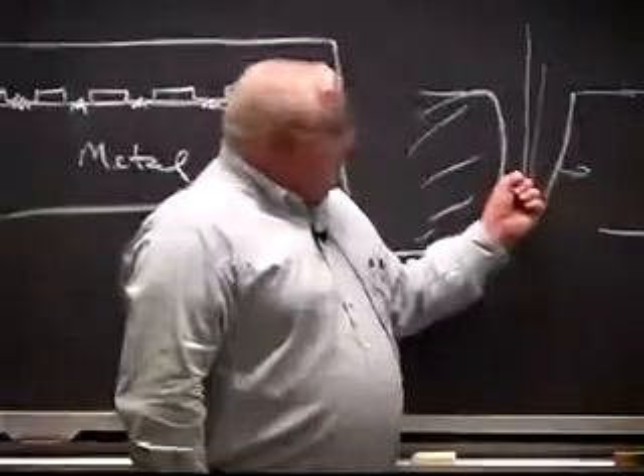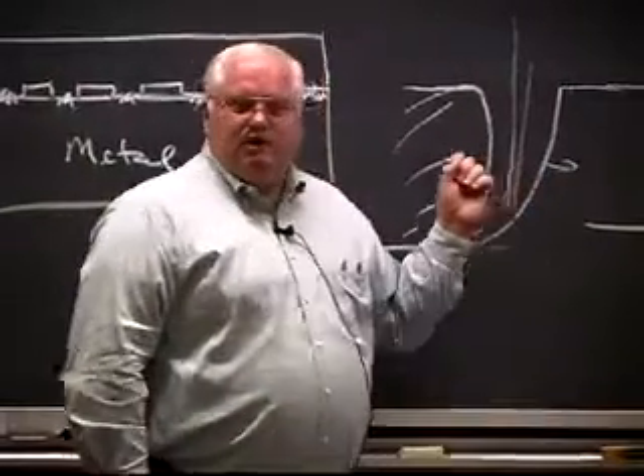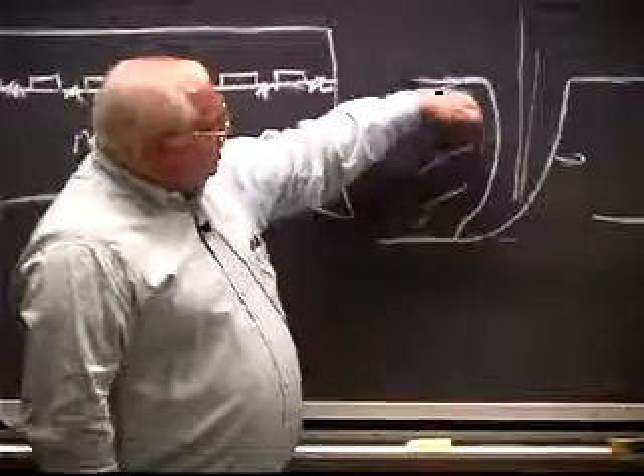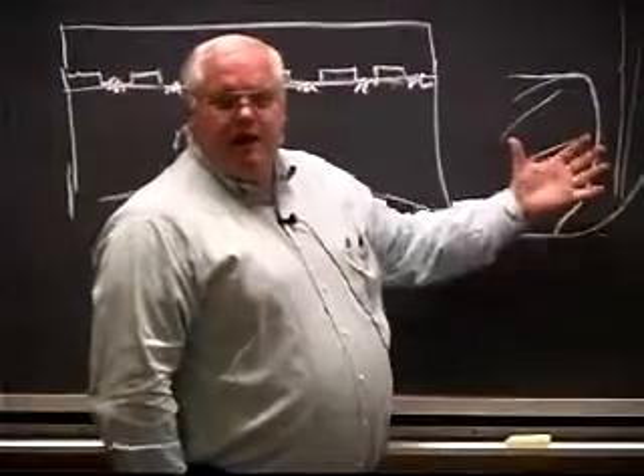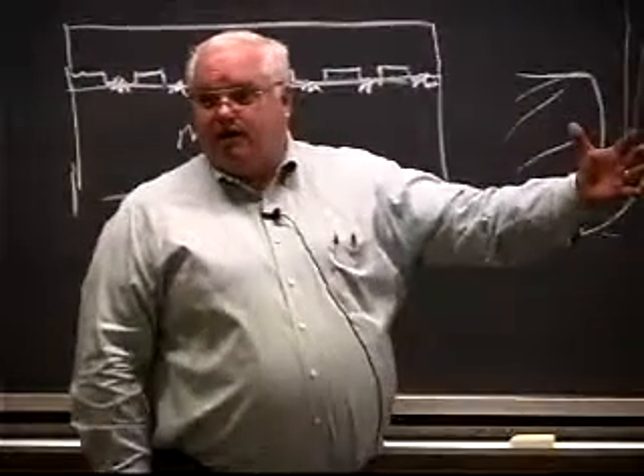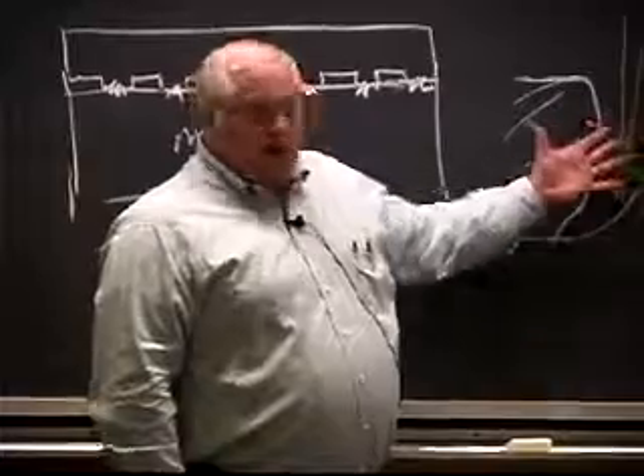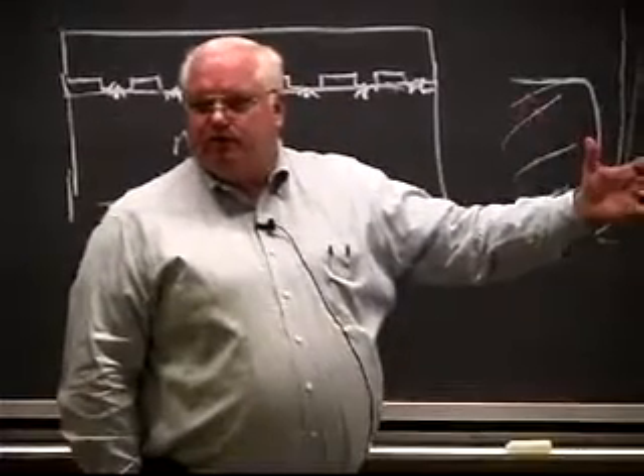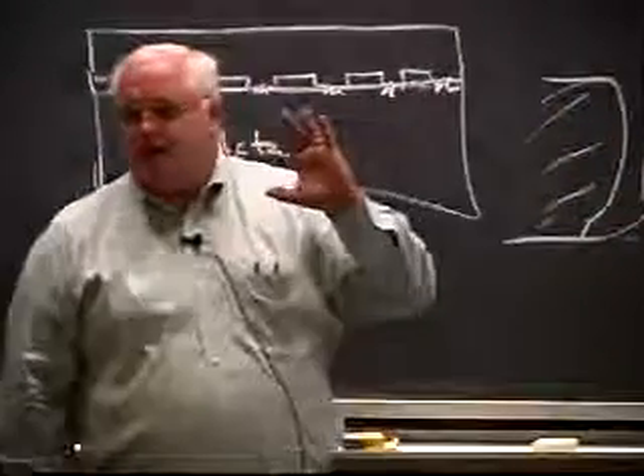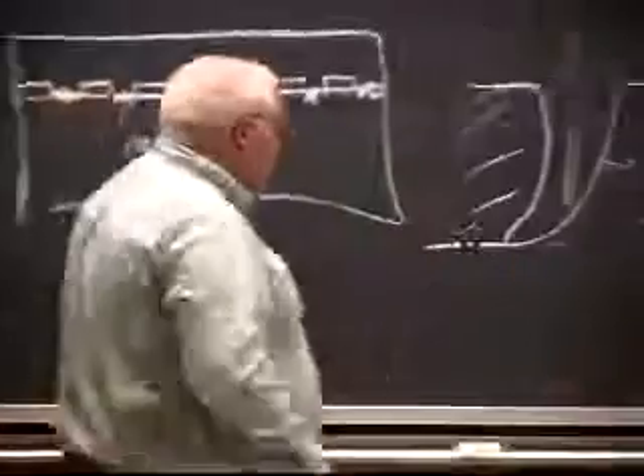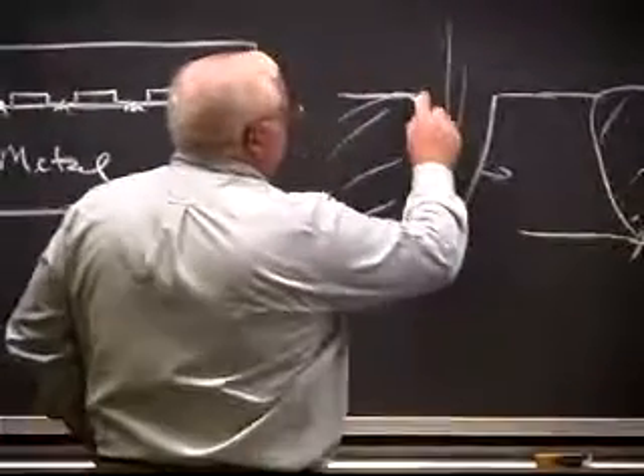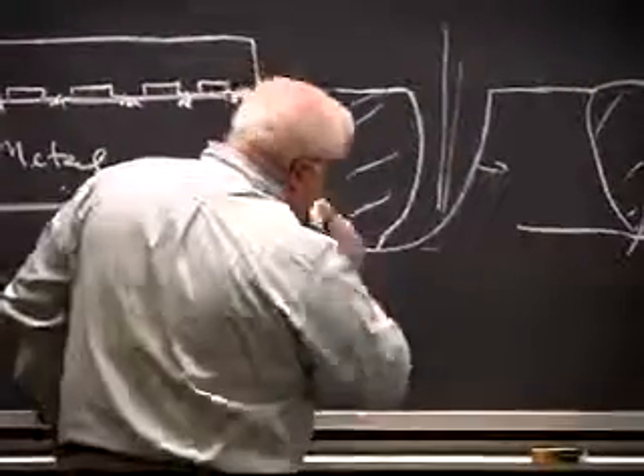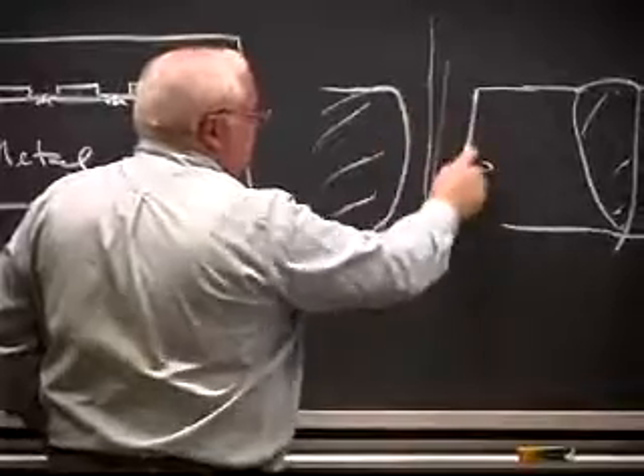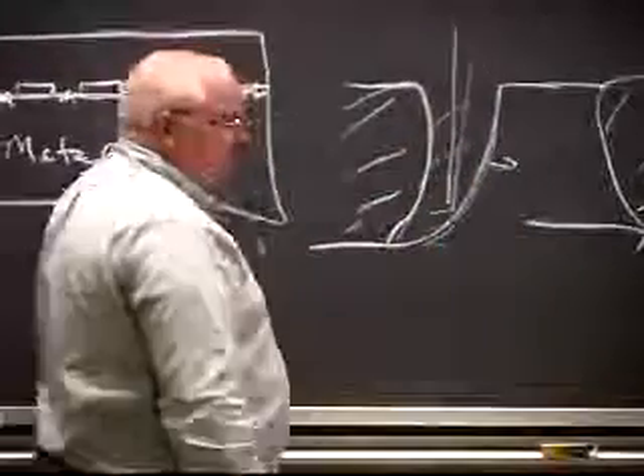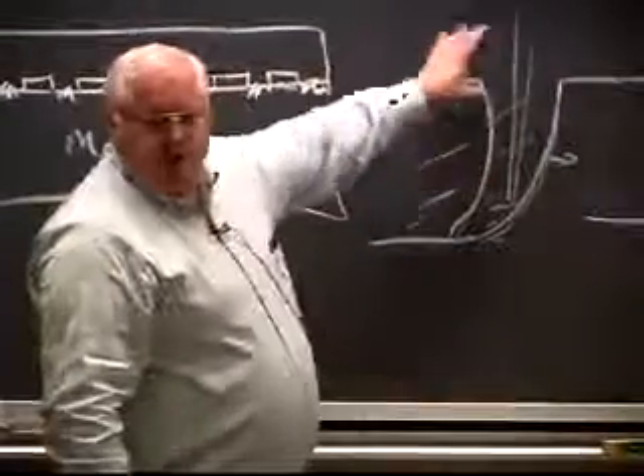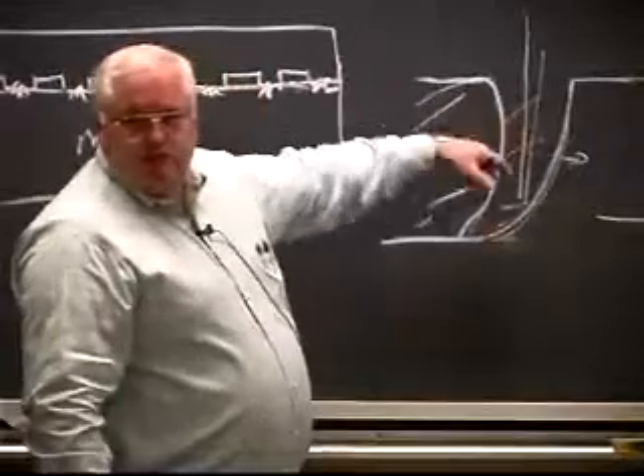in welding might be interested in. And in the electron beam, what they do is they weld on aluminum with an electron beam, and they use the X-rays that are generated by this 100 kilovolt electron beam that go through the aluminum, and they basically take an X-ray, a high-speed X-ray picture. And so you'll see, you have to look carefully, you're going to have to close the shades. Actually, you'll just see kind of a lot of gray, but you'll see a slightly different color gray in the beam hole region, and you'll see the beam bouncing around, and the bouncing around of the beam relates to some